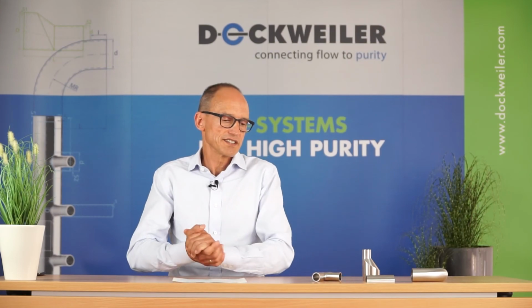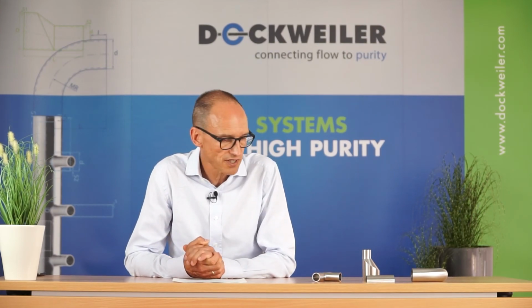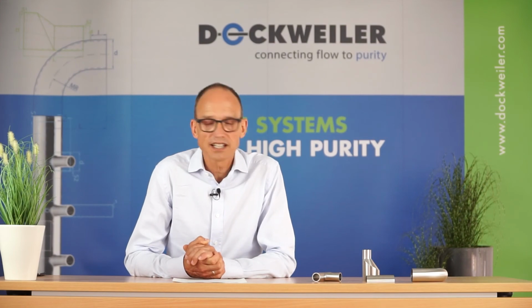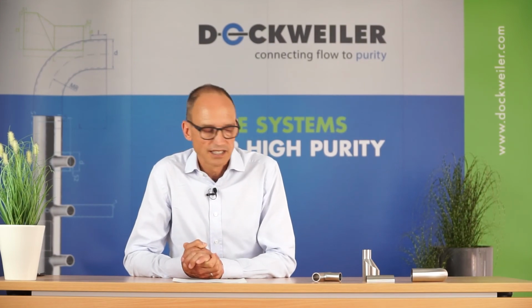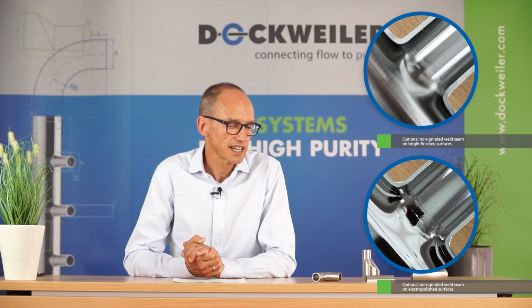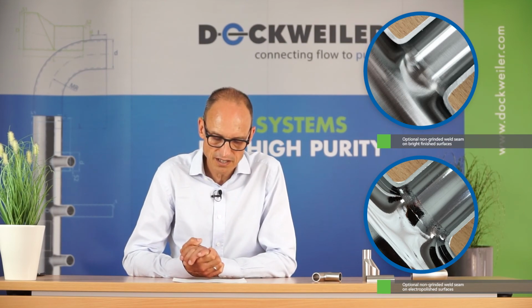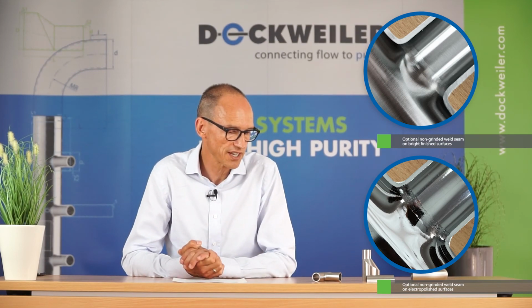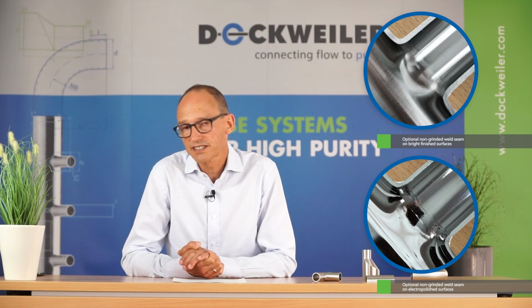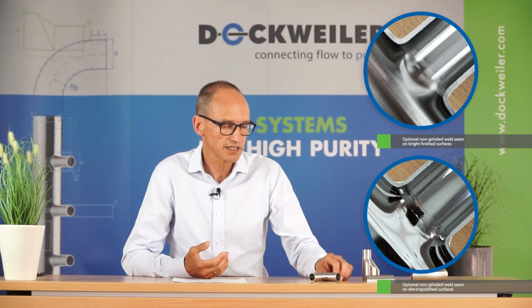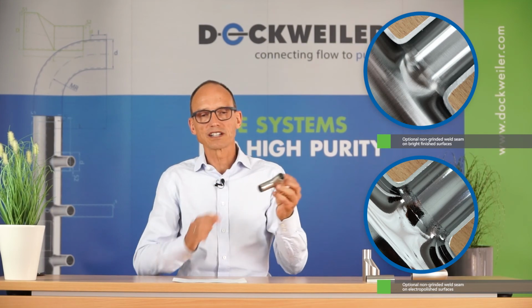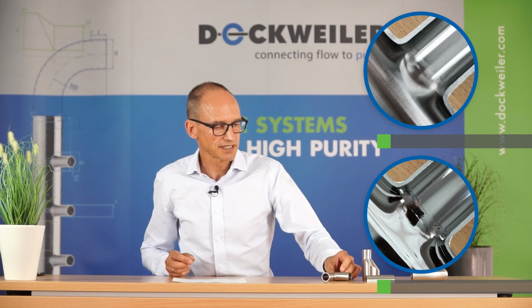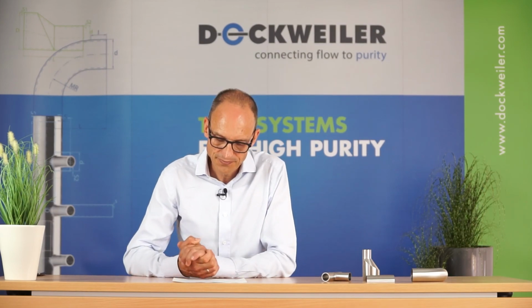So this is the first option, and the second option is to leave that T-piece weld in the as-welded condition that has to meet the requirements of Table 18, which I mentioned earlier, and would be exactly the same requirement on a weld as the three other welds on the T-piece when getting installed need to meet. So that's the overview about the new revision of DIN 11865. The English translation is coming out soon.